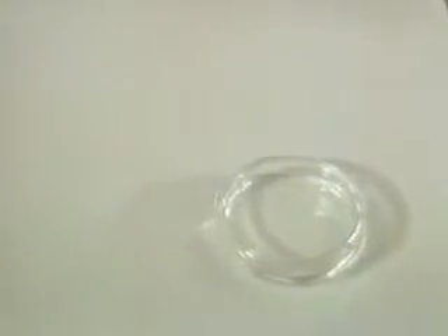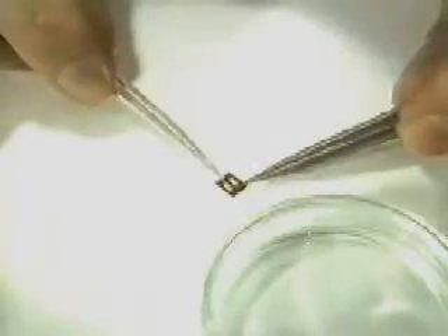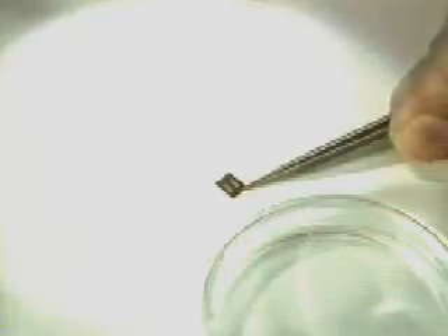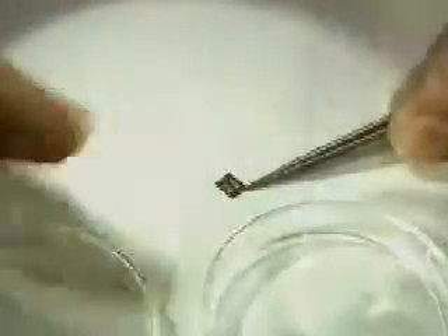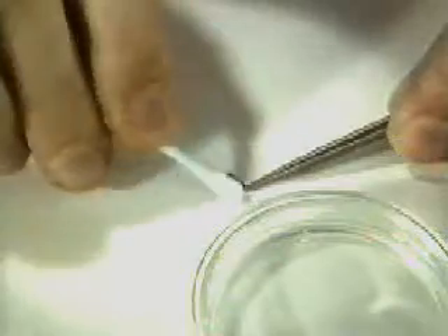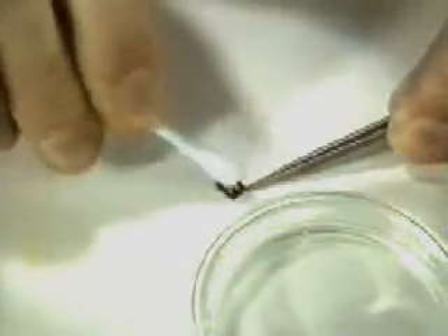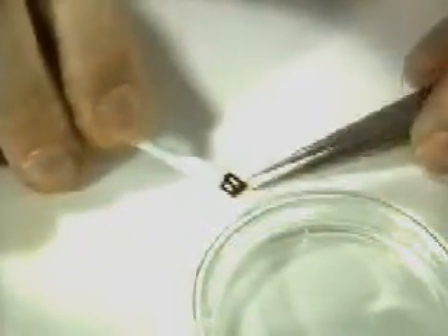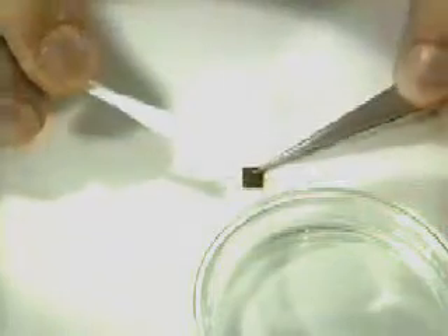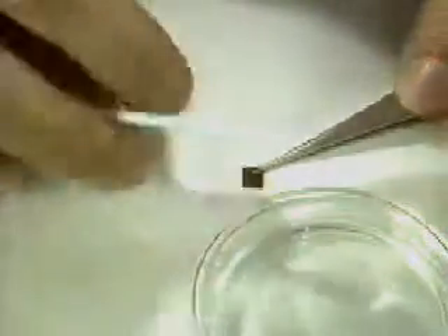The solder terminals are cleaned from both sides with a cotton bud soaked in solvent. While doing this, the solder terminals are held with a pair of clean tweezers, not with the fingers. Each cotton bud must not be dipped into the solvent twice, so that it does not become contaminated.